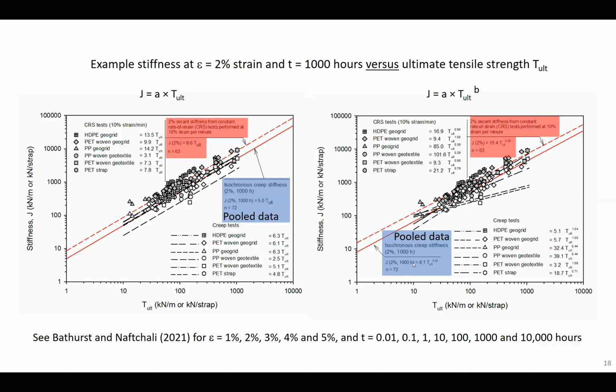So here you can see the highlighted portion in red. Again, it shows the relationship between the secant stiffness of the material and T ult taken directly from a constant rate of strain test. And you can see that this curve gives you a coefficient of proportionality, for this in-air constant rate of strain test, which is higher than the pooled data result, which again shows you that these constant rate of strain tests have to be used with caution because they're going to overestimate the stiffness of the material.